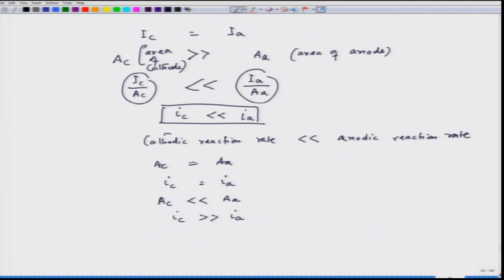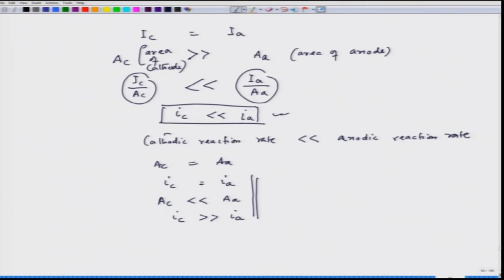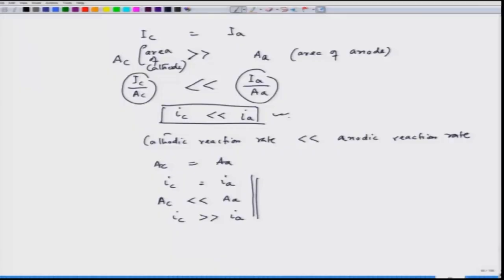Now, what is interesting is that in this situation the anodic current density is very, very high compared to the other situation we have considered. So, the dissolution rate of the anode would be so fast if we have a larger cathode area compared to the anodic area. The anode will dissolve in order to meet the electron requirement for the cathodic reactions happening on the cathode surface. So, when we see the current density, we are able to understand this phenomenon more clearly, and scientifically it is more intriguing than considering it from an analytical point of view. That means the current density is an extremely important consideration.